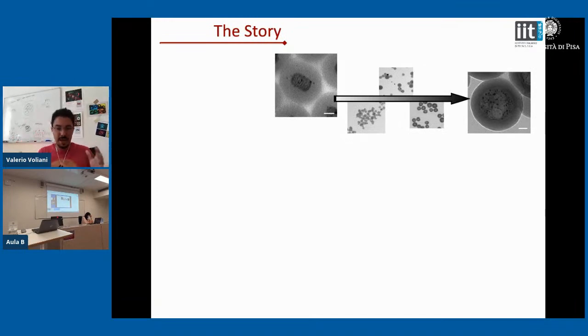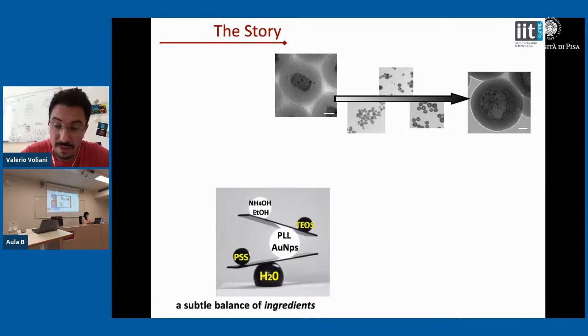Now, a little bit of history behind the passion fruit-like nanoarchitectures. During my first postdoc in Spain, a lot of years ago, I was working on converting nanocrystals, and I was trying to modulate the emission bands of these crystals by introducing ultra-small gold nanoparticles in the structure. Every time that I did the synthesis, I obtained some strange byproducts. By the way, at a certain point, I looked at these byproducts and I understood the potentiality of this kind of structure. So I then started to optimize the synthesis in order to obtain the standard protocol that we are now employing for the production of the nanoarchitectures.